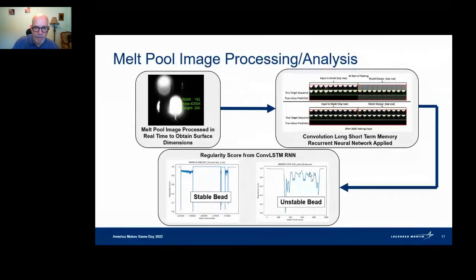The relevance here is that we're able to take the in-situ process monitoring data, particularly in this case the image data, and we're able to predict from that when our process is headed to an instability. Jack's team has been working, unfortunately I was not able to get those results in here, with the IR data as well, and they are getting similar results. Those data are able to predict through the neural network when that instability is about to occur.